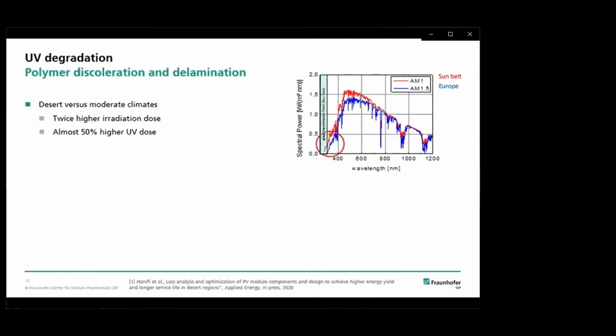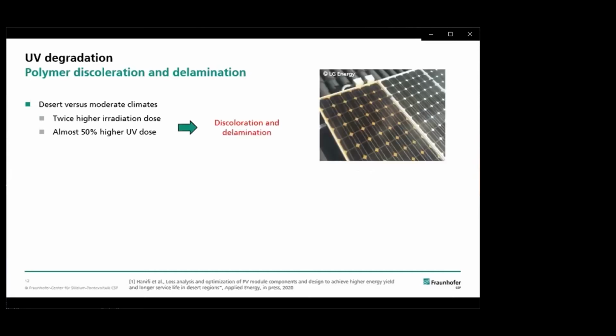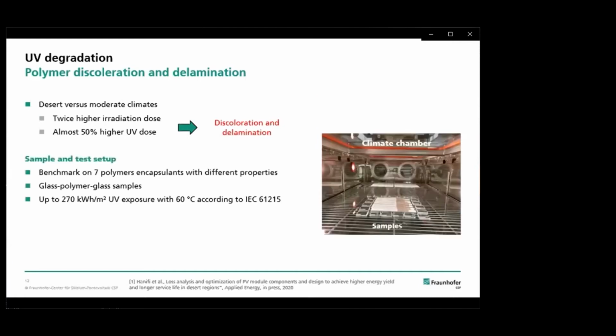Now I want to jump into the topic of UV degradation. As we have seen before, in the deserts we could have twice higher irradiation doses overall, which means also higher UV dose. But in addition to the irradiation, we also have a spectrum-dependent component, further increasing the UV dose by about 50%, which is because of the AM1 compared to AM1.5, which you have in the typical climates. And this will lead to discoloration and delamination, as we have also shown before.